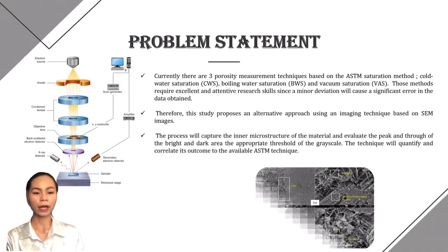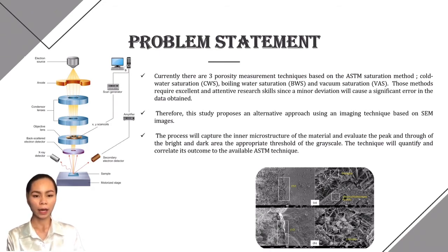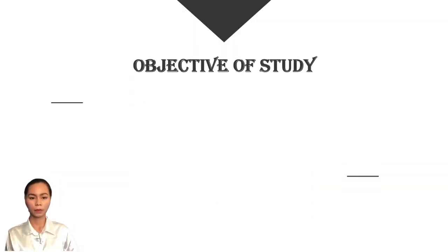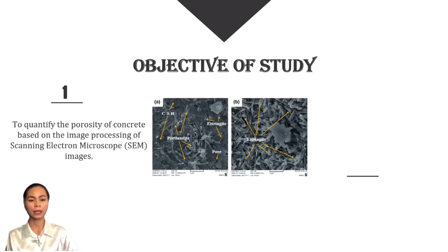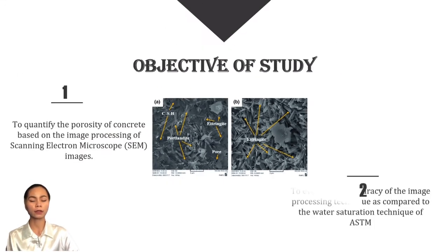In this method, we will capture the inner microstructure of the concrete and evaluate the bright and the dark areas, using the appropriate threshold of the grayscale. The result will be compared in terms of porosity value with the available ASTM technique. The main objective of this study is to develop an image processing technique that will be compatible with the SEM images of concrete. Meanwhile, the sub-objectives of this study are to quantify the porosity of concrete based on the image processing of scanning electron microscope images, and to evaluate the accuracy of the image processing technique as compared to the water saturation technique of ASTM.